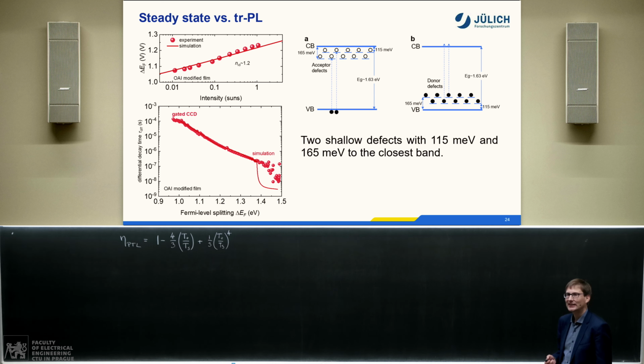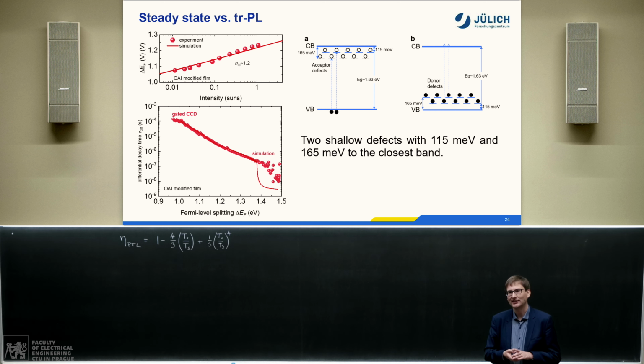And then we tried to fit the stuff. And then we know that, in Shockley-Read-Hall recombination, most people write the Shockley-Read-Hall equation just for deep traps because then it gets nice and simple. But if you look up in a textbook, you get the whole thing. It's not simple, but it has a few more terms. And I don't bother you with the equation, but if you add one shallow trap, you can get it on this slope for a while, but not for that much.